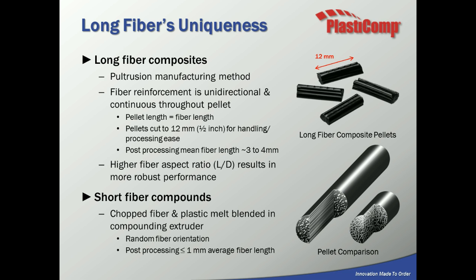So what makes long fiber materials unique? Our materials are made with the pultrusion process. If you look at the bottom right-hand corner of this slide, there are two pellets. The longer pellet is made with a pultrusion process. And what we get with that is unidirectional fiber alignment throughout that pellet. Also, the pultrusion process gives us the capability to fully wet out or coat those fibers prior to the injection molding process. And that's important because that coating of the fibers protects them during the molding process and maintains fiber length in the final part, which leads to higher mechanical properties.